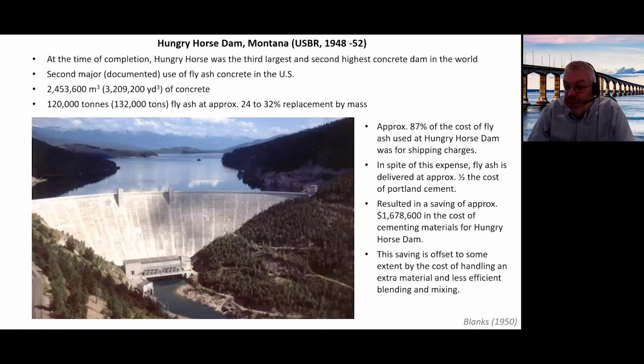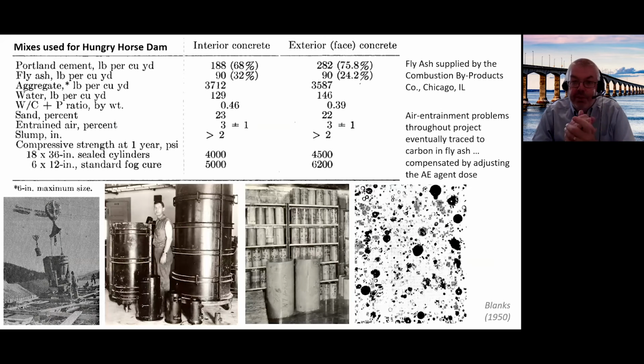The fly ash was actually shipped all the way to Montana from Chicago, Illinois. Despite the huge cost of the shipping, it was still half the cost of Portland cement, and this resulted in what was then a considerable saving in the cost of cementing. Here are the mixes that were used. So in the mass concrete, up to 32% fly ash was used in the concrete.